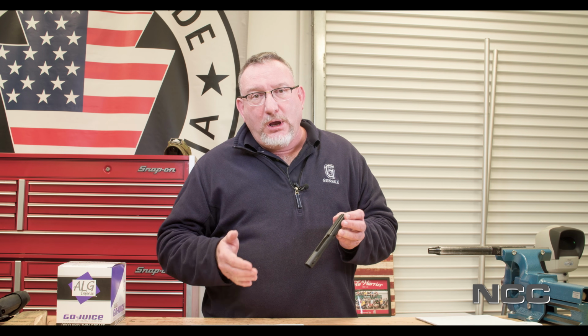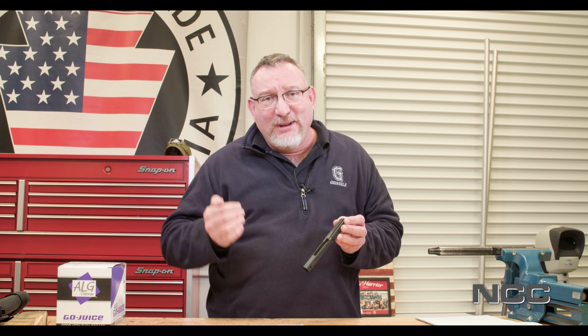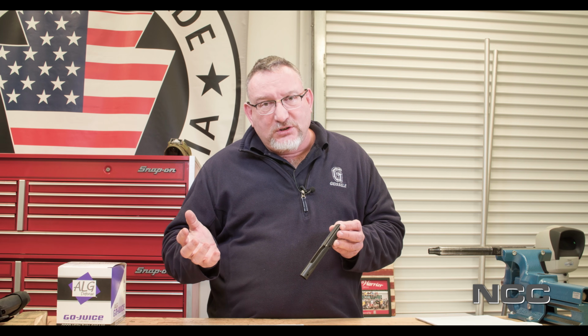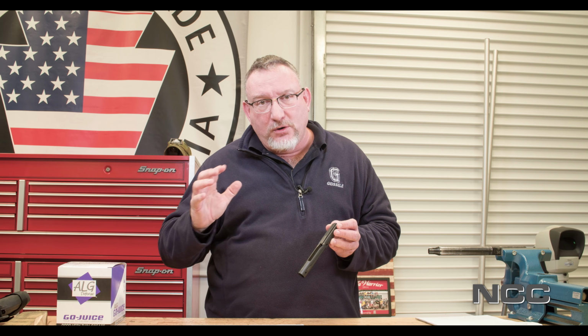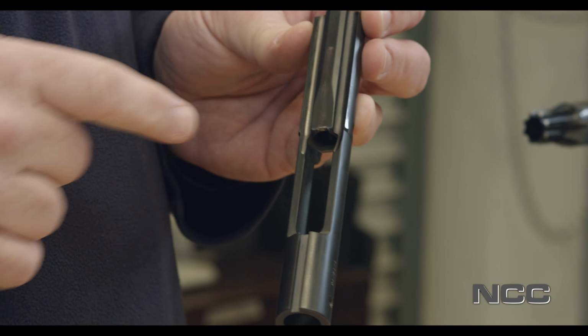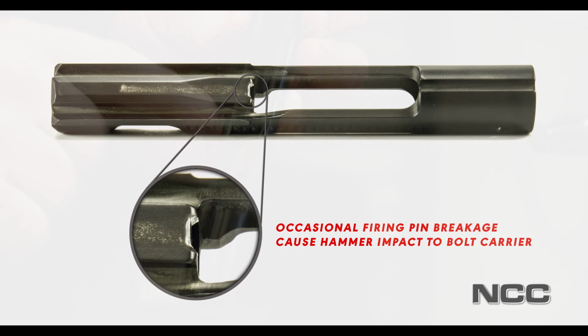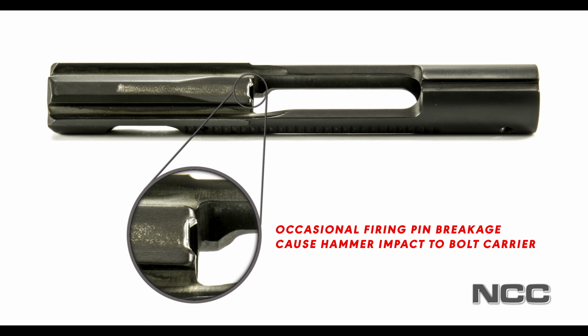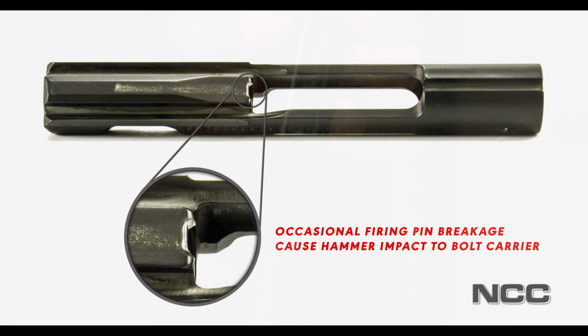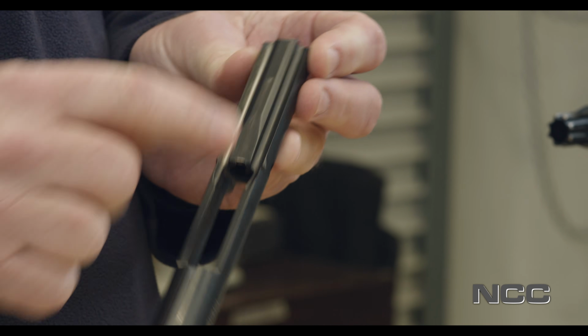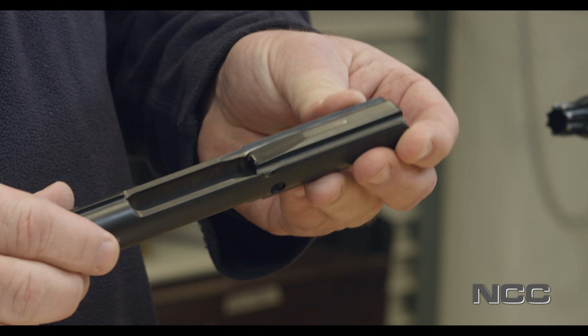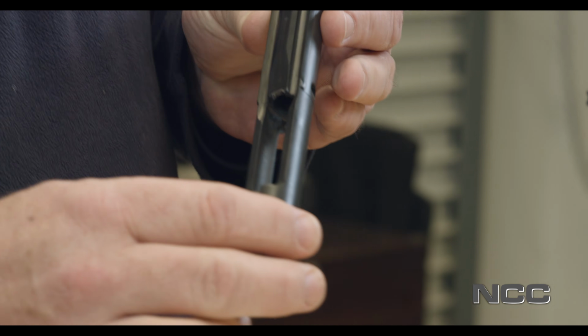Basically, our cyclic tester runs at 600 rounds a minute. It runs like an automatic weapon. And it's extremely hard on the components, and firing pin heads snap off on this thing on a regular basis. So you have to have somebody monitoring it, and when a firing pin breaks, the hammer goes in and smashes into the bolt carrier. So you see what that has done. That's because the hammer smashed into that thing thousands of times. But if you look on this right here, you can hardly see that the coating has worn off.